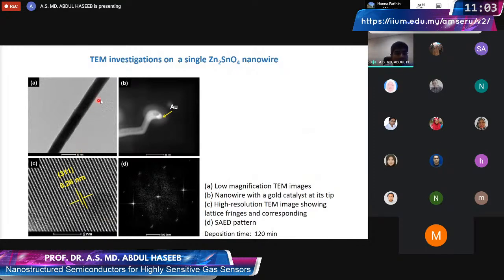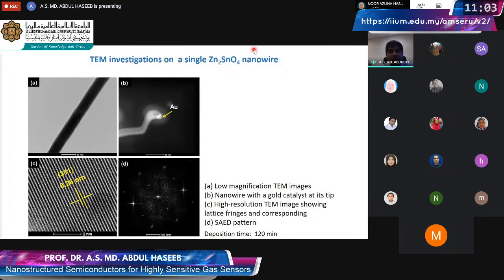The nanowire that we get has a 311 plane, which is parallel to the growth direction. And then we have a lattice parameter which matches a mixed oxide, and I'll show you the mixed oxide now. I already wrote it down. So it's not a separate mixture of tin oxide and zinc oxide. It's actually a ternary oxide which contains zinc and tin.